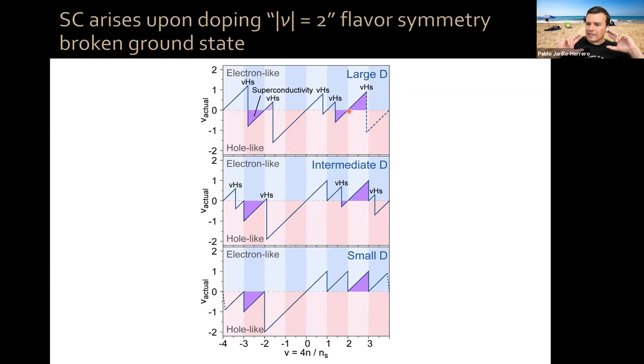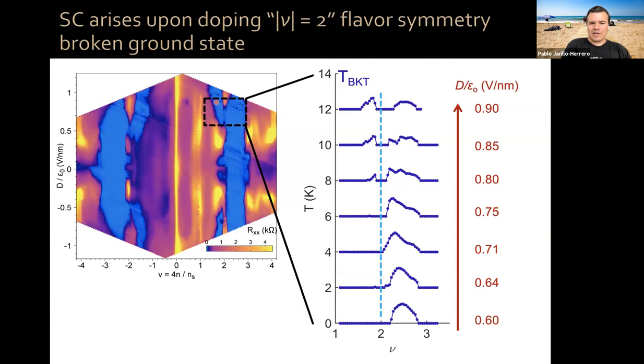Because it's kicking in the phase transition to a flavor polarized phase with two Fermi surfaces before nu equals 2, it means those two Fermi surfaces have to be hole doped. Because you have 2 electrons per moiré unit cell in the flavor polarized phase, the Fermi surfaces which are still open must be hole-like because this occurs before nu equals 2. So this region of superconductivity had to be hole-like. And indeed, in our Shubnikov-de Haas oscillations, we see that those carriers are hole-like. So this gave us the clue that the important thing for superconductivity to emerge in the system, as you dope either with electrons or with holes, is the many-body ground state, which has two open Fermi surfaces.